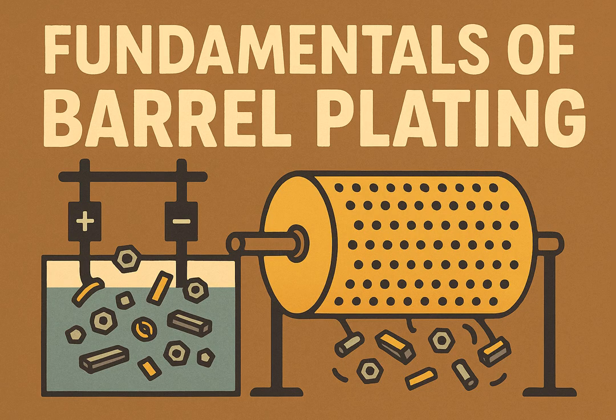How is the electrical current density controlled for the whole barrel load, making sure enough power gets there? Good question. Current density, which directly affects the plating rate and quality, is maximized by placing the tank anodes, the positive electrodes in the plating bath, as close as possible to the barrel exteriors. Get the power source close to the target. Right. For horizontal barrels, using anodes that are contour curved to match the barrel's circular profile can significantly increase current density by maybe 10-20%, according to P2 InfoHouse, because it minimizes the distance the current has to travel through the solution.